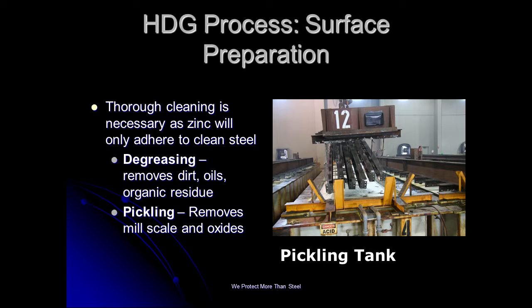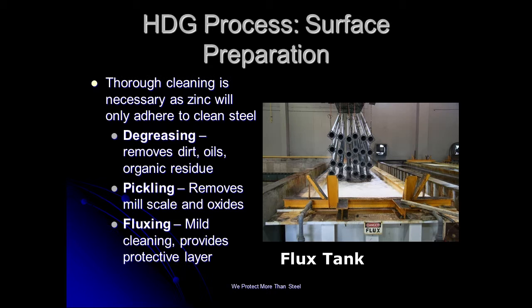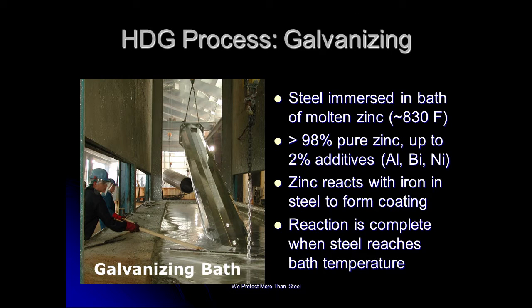Once the steel is totally clean, what's the first thing that steel is going to want to do? Yeah, it's going to rust, or oxidize, because it's totally clean and it's moist. So we come out of the pickling bath and go into a flux bath. The flux bath does three things. It preheats the steel to 160 degrees, puts a light coating on the steel to keep it from oxidizing, and helps the zinc flow a little better. After it comes out of the flux bath, it goes into a zinc bath. In America, we heat most zinc baths to anywhere between 830 and 840 F. To meet the ASTM A123 spec, we have to have a minimum of 98% pure zinc in our kettle. And you have this iron diffusion process where the iron is coming out and the zinc is going in, so it's part of the steel.